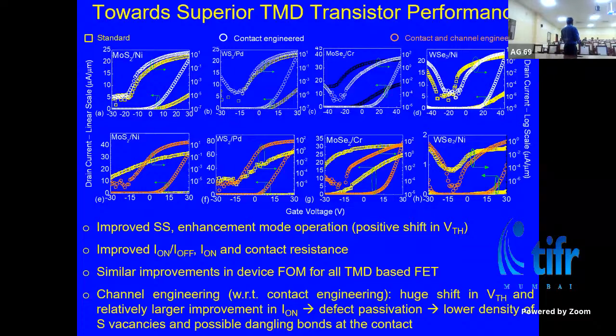What we found is that these two TMDs behave intrinsically N-type because of the sulfur vacancy under certain MBE scenarios. The sulfur vacancies introduce donor states, and that's why they become N-type. So if you have to make it intrinsic, you have to passivate the sulfur vacancies. And we found that the sulfur interstitials that we are bringing in also passivate the sulfur vacancy. So in the channel, the material does not change if you don't bring in new material. In the channel region, we are only bringing the interstitial, and wherever there is a vacancy, it passivates the vacancy; the material is still intact. It's the same channel, same character. But in the contact area, when we break the material, we have this new hybridized state, new bonding channels formed, and better transfer.